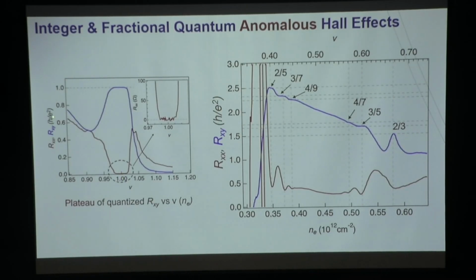The Rxy is perfectly quantized at h/e², while the Rxx is only a few ohms, within the noise level. So this is as good as any quantum Hall data you get from a two-dimensional electron gas in high magnetic field. More interestingly is what happens at these fractional filling factors of the Moiré superlattice. Last year, we had a total of 6 fractional states. At 2/5, 3/7, 4/9, all these fractions follow the so-called Jain sequence, if you're familiar with it, with odd denominators. And you get quantized Rxy appearing as plateaus, and you get dips in Rxx, as you would expect for the fractional quantum Hall. At that time, these dips were not very small. The smallest value you get here is probably like 7 kilo ohm, which is far from 0, and that's not ideal. But clearly, we have observed the fractional quantum anomalous Hall effect at zero magnetic field in this setting.